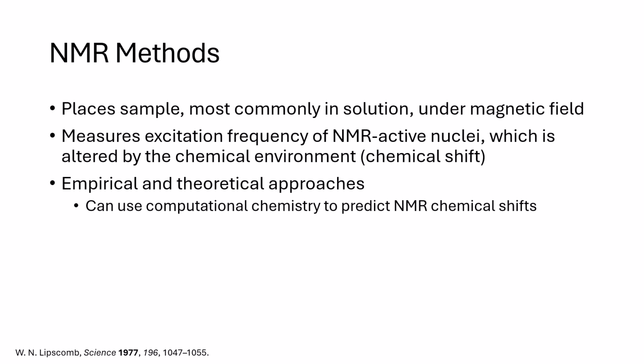Aside from crystallography, the other important physical method to this discovery is NMR. In NMR, researchers place samples, most commonly in solution, under a magnetic field and measure the excitation frequency of NMR-active nuclei, which is altered by the chemical environment and reflected in the chemical shift. Lipscomb recognized the importance of NMR to structure determination and came up with empirical and theoretical approaches for using NMR. In the empirical approach, researchers observed the chemical shifts of boron in different boron clusters, while in the theoretical approach, computational chemistry was applied to predict NMR chemical shifts.